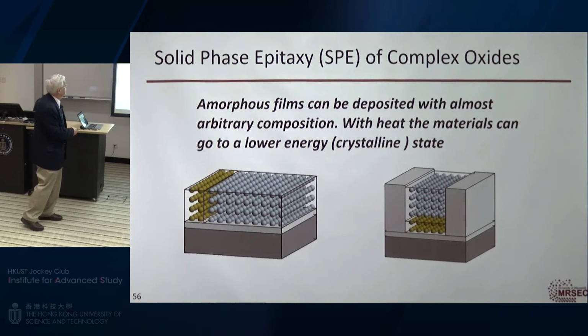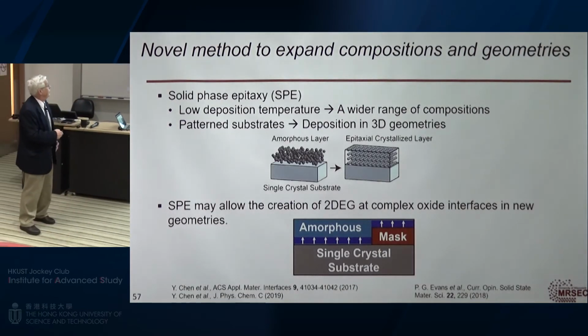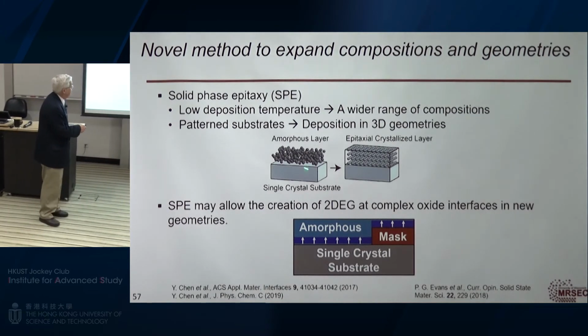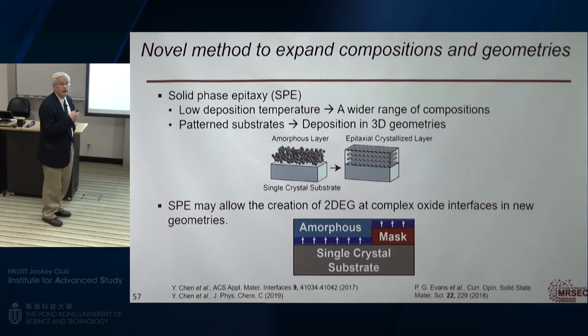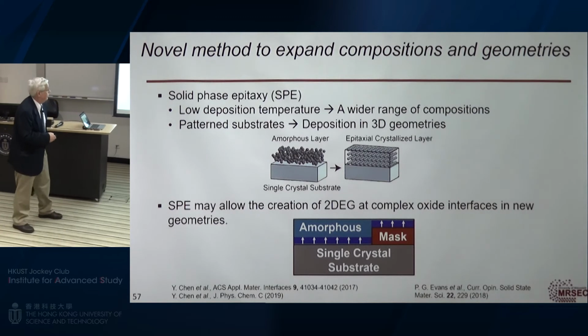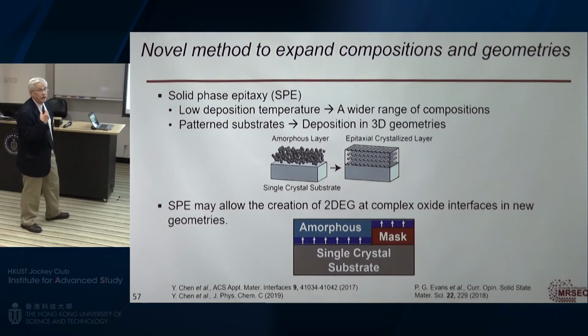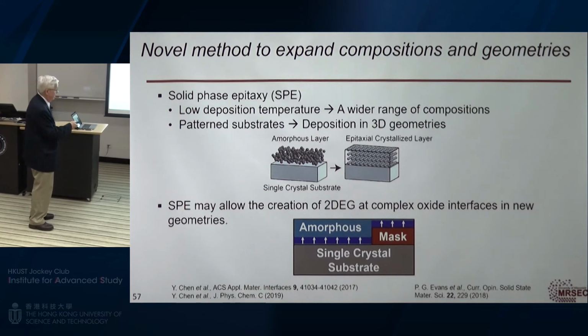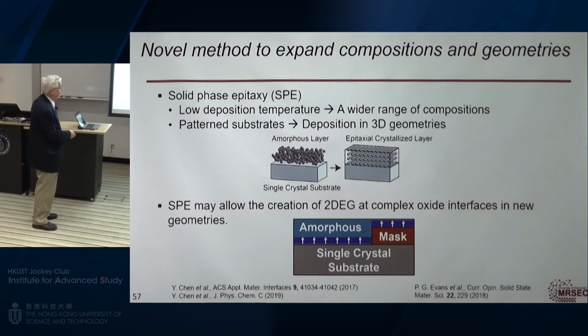To do that, there is a process called solid phase epitaxy. It basically anneals the material at a low temperature. We also can deposit amorphous material into very complex geometries using atomic layer deposition. This amorphous layer could be something that is metastable, in the sense that if I tried to make it by conventional techniques, it would phase separate. But if I put down the amorphous layer, let's say by sputtering or pulsed laser deposition or atomic layer deposition, I can put down an arbitrary composition. And then if I heat that up, I can use that reordering to keep the material from phase separating. I can make a homogeneous alloy.